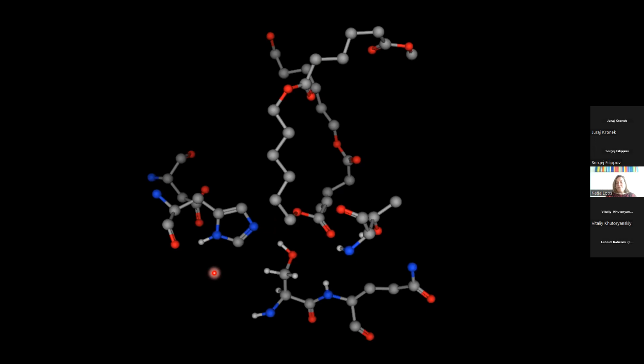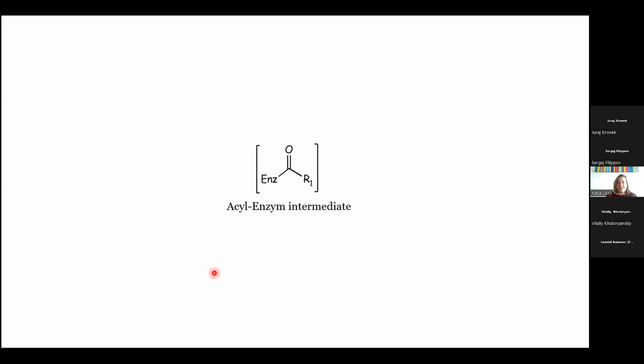And very often people ask, are you sure it's the enzyme? Yes, we are sure because we do a lot of blank experiments. So we do the same experiment without the enzyme, with just the acrylic beads. We cook the Novozym 435 in an oil bath so that we know that the enzyme is dead. And then you get no polymers. So it's really the enzymatic activity, but it's very amazing that that works, because there are a lot of limitations why you think it should not work, but it works. So the important thing in this whole synthesis is that the acid reacts with the serine, and we call this an acyl enzyme intermediate.